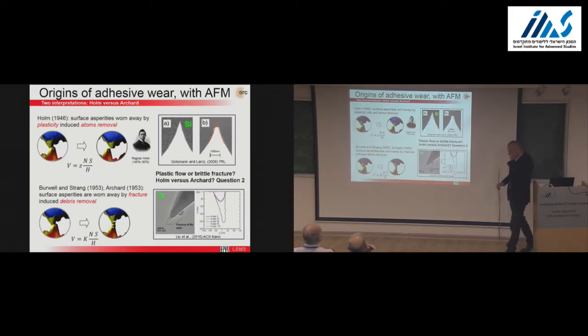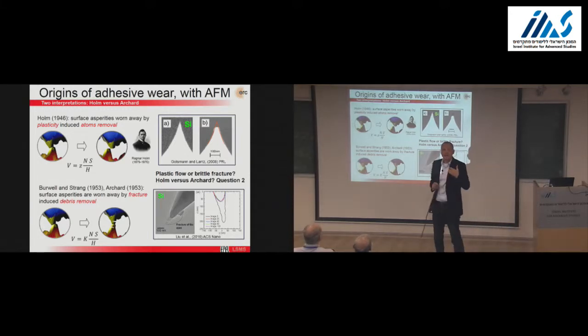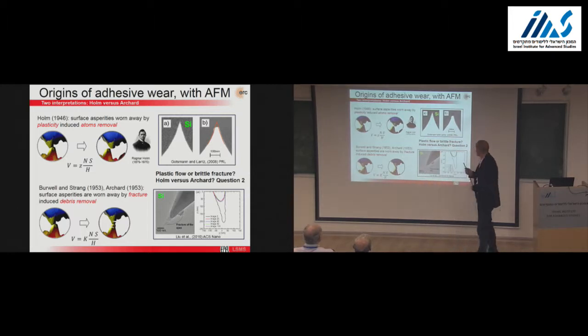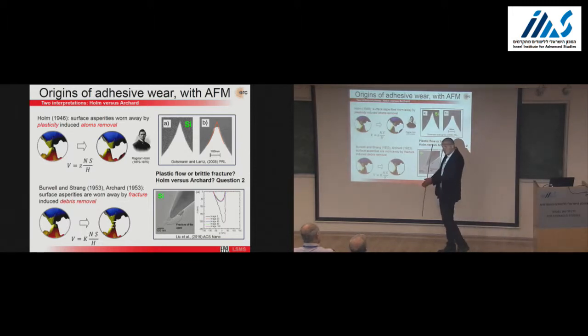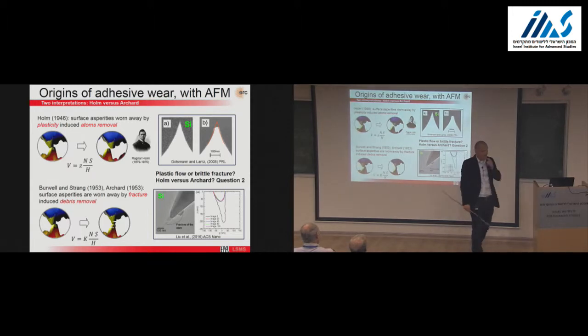So more recently, there's been a lot of debate in the literature about the validity of Archard debris formation process when you go to nanoscale, based on very recent AFM atomic force microscopy experiments. So here I'm showing some data from a group in Switzerland, Gotsmann and Lantz, where you have this very sharp AFM tip that you drag along the surface, and the tip gets rounded. Okay, it smoothens, and you don't form a debris. So usually that's what you observe when you go to small sizes, when you have very sharp AFM tips.